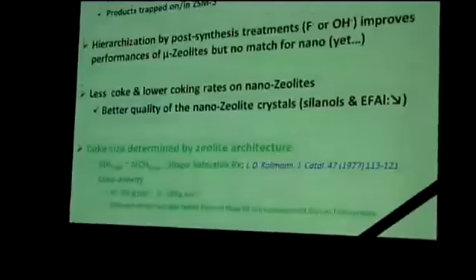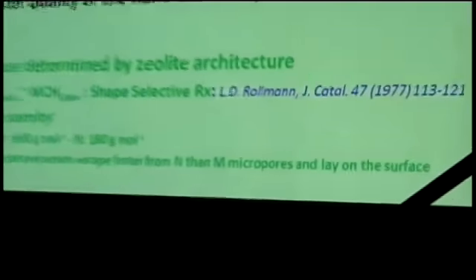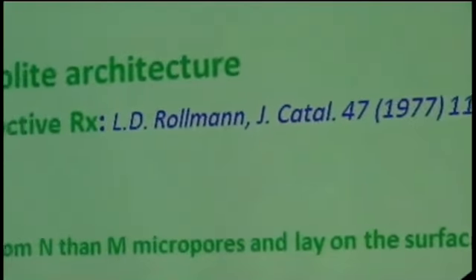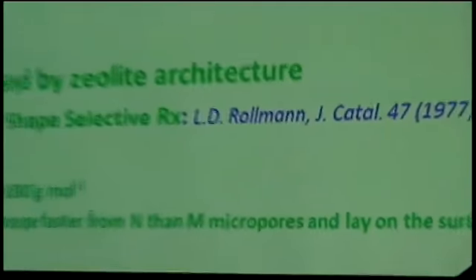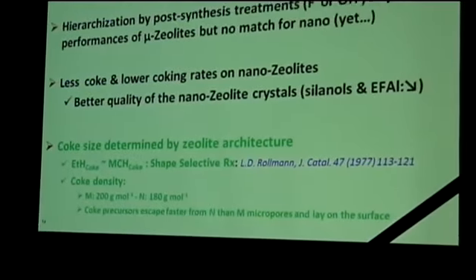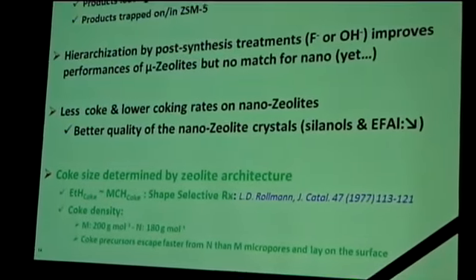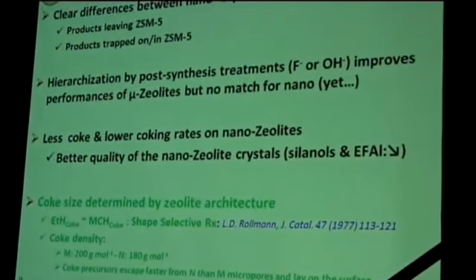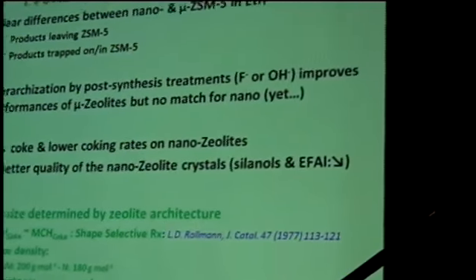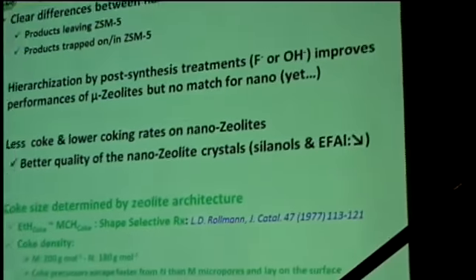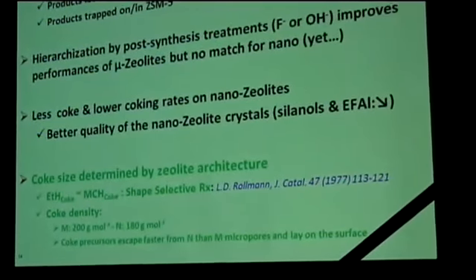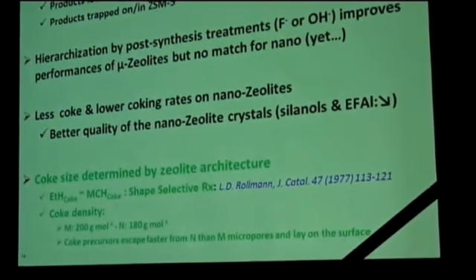What we already know from other studies is that, in general, nano-sized zeolites, if they are prepared properly, have a better quality. By better quality I mean they have fewer defects, far fewer internal and external silanols than the post-synthesis treated material, because that material receives a lot of shock and destruction, and one sign of that is the presence of extra-framework aluminium. I will not go into this, it was already mentioned.